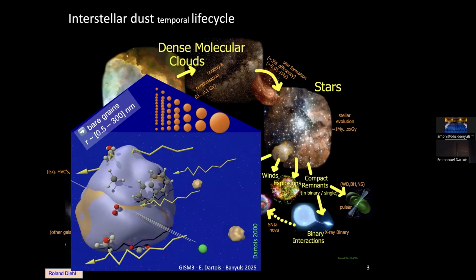There have not been a lot of plots showing you the size distribution you expect for this dust grain, because this is an important aspect. If you look at the diffuse interstellar medium, typically you will have bare grains made of, we'll see, refractory solids with sizes between 0.5 and 300 nanometers typically, and with a power law size distribution, which means that all the processes requiring a surface are generally dominated by the small sizes, but the majority of the mass is in the large grains if you integrate these grains.